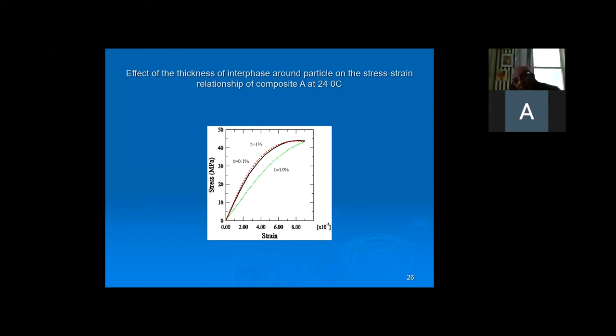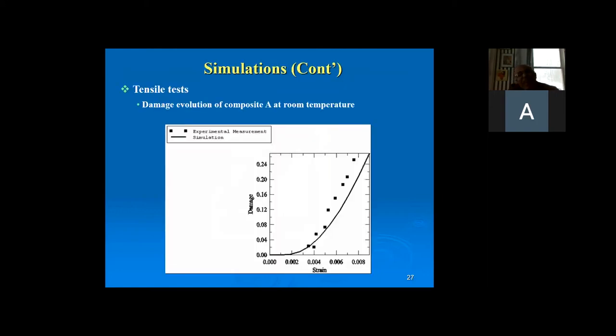Again, so we also, if you change the thickness of the glue between the particle and the matrix, of course, you change the stiffness of that interface, and we try different thicknesses. And then we look at the damage in the system as a function of these parameters. And this here, the filled square is experimental measurement, and the solid line is the simulation from unified mechanics theory.